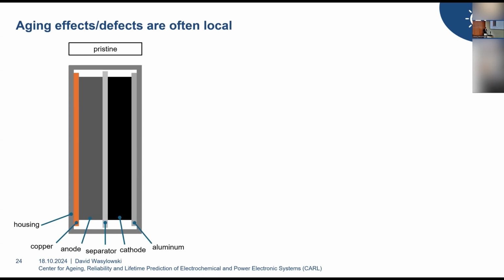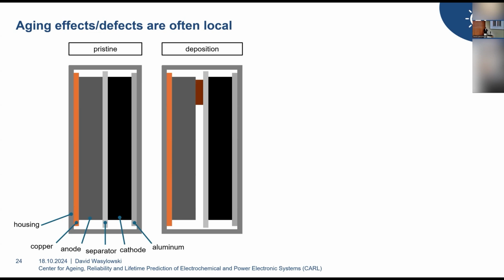And so now, just to introduce a few aging effects, you don't need to understand them all in detail. We will do this later on in the presentation. But if we would just now introduce a local design flaw within the cell or a manufacturing defect that is, for example, blocking the pathway between the cathode and the anode, preventing lithium ions from intercalating into the anode, and, for example, just being deposited on top of it, we would get this local deposition, which is this brown part here on the top of the battery. So typically, these deposits consume a large chunk of lithium, which is then not really longer usable for further cycling. So this is something that might occur locally, and we really want to prevent.